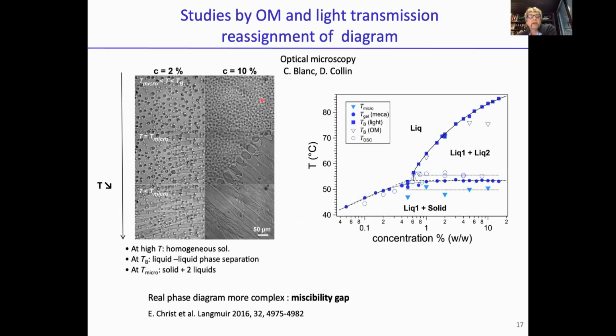We just made a simple optical microscopy here. In this area, when the gel melts, it doesn't melt to form a liquid, it forms a biphasic liquid. So we have a liquid-liquid phase separation here. It means that this phase diagram is more complex, and we have a liquid-liquid domain here. You can see clearly here, when the gel forms, it forms this kind of spherical object that becomes a solid. So we have droplets of solids that are included in the fibers, which explains the morphology of the gels.